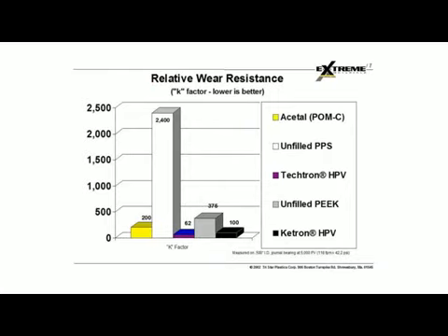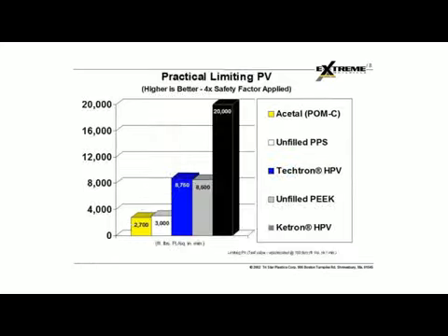This next chart shows the relative wear. When we talk about wear factor with plastics, we're talking about their K factor. And so you can see here that the Techtron HPV has a K factor of 62, which is less than the acetal materials. It's less than the Ketron HPV, which is the bearing grade PEEK. And obviously it's a much better material over an unfilled PPS or an unfilled PEEK. So as you can see, the wear factor is very, very low on this material relative to other materials.